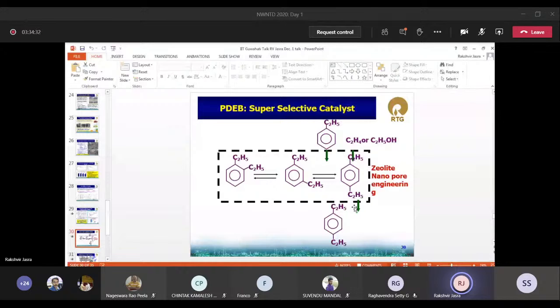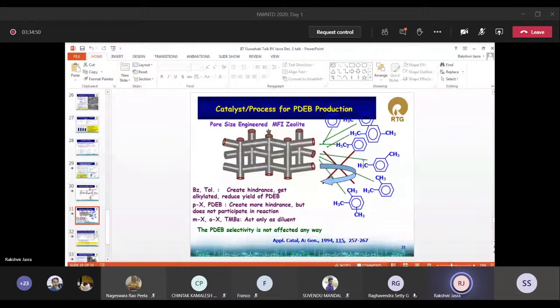You see, the pore size is only 5.2 by 5.6 elliptical. Only a fraction of an angstrom control of the pore so that only paradiethyl benzene is coming out. That's what we did. You can see this red circle here, this is the pore opening of the zeolite, which is our catalyst. This we have controlled by a few fractions of an angstrom, maybe 0.2, 0.3 angstrom, by depositing some inorganic material on the pore very cleverly. This is really nano engineering of pores in practice on a commercial scale. So this really made it possible to use a feedstock which was not pure ethyl benzene, which was available to us as a mixture of C8 aromatics. We said we'll use it because only ethyl benzene can get into the pores.